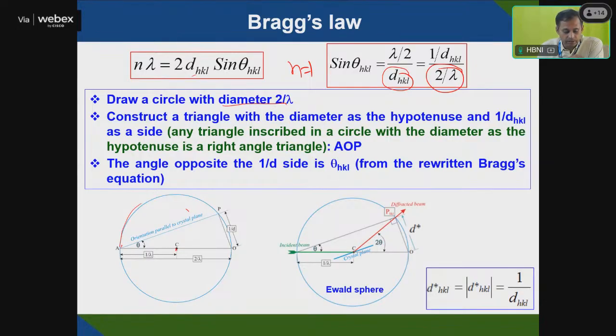Then I draw a triangle with P, a point on the circle. A to P I join with O. I get a triangle constructed with the diameter as the hypotenuse, and 1 by d HKL as one of the sides. So the total diameter is 2 by lambda, and this is your AP, the hypotenuse, and this is 1 by d. The angle opposite the 1 by d side is theta HKL. Now you put a crystal plane here. This is your sample. Your incident beam is falling in this direction on the same circle, and is diffracting at this angle theta.